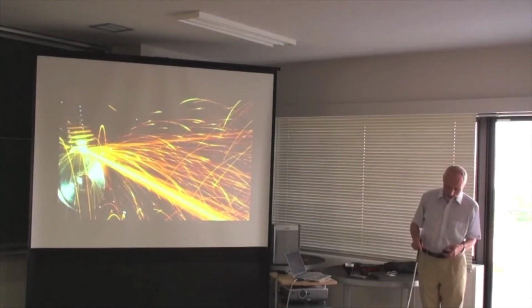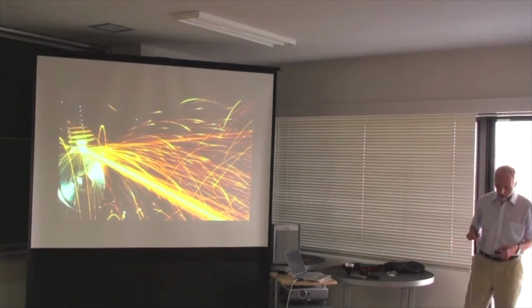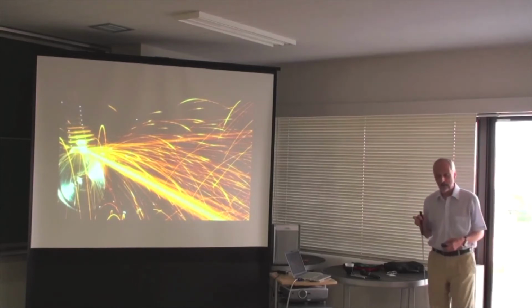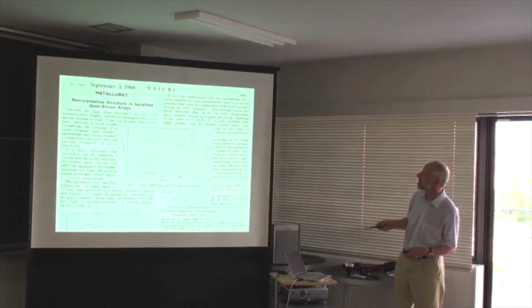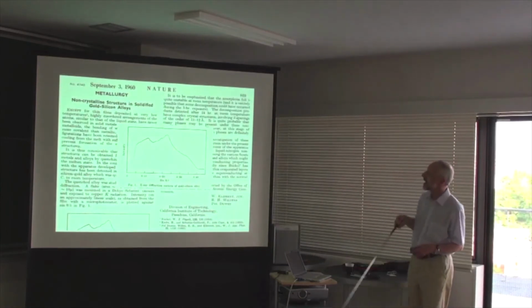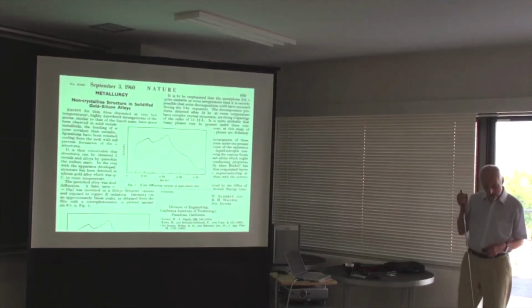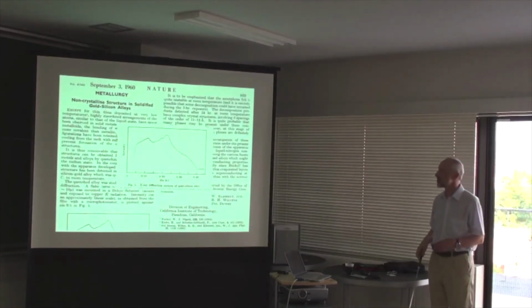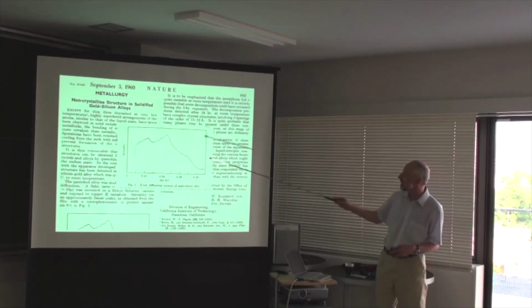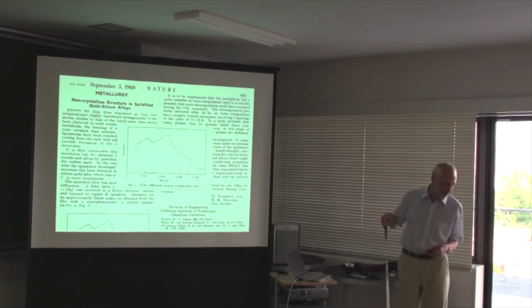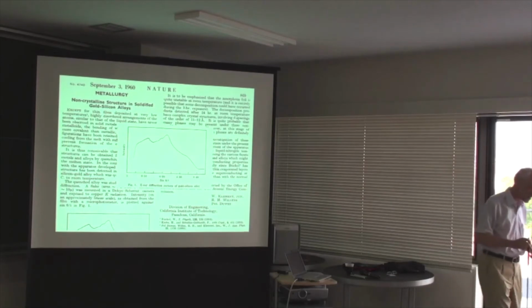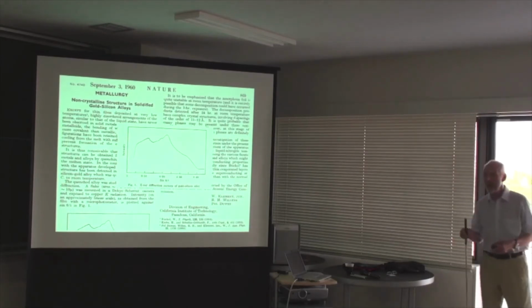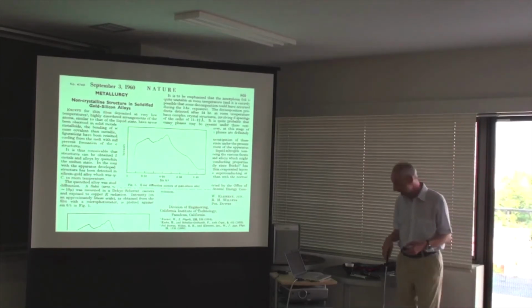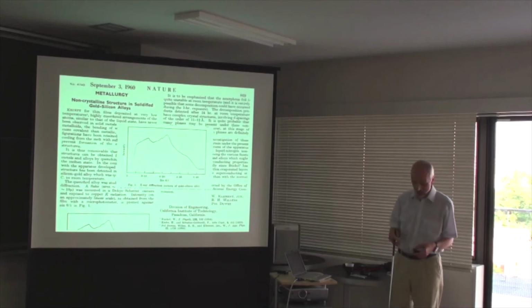You might be interested that the first report of metallic glass made from the liquid was in 1960, here's the paper from Nature. They used an even more extreme process, little splats onto a substrate, not a continuous production. This is the X-ray diffraction trace. Probably wouldn't get past the Nature referees today, but it turned out to be a real result. They had made an amorphous material.